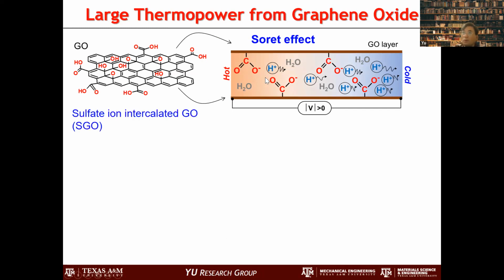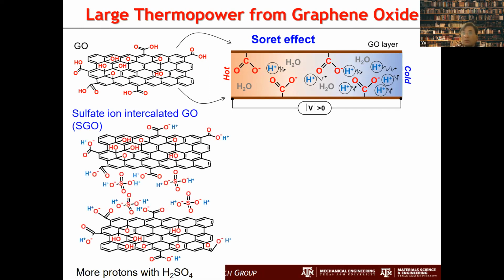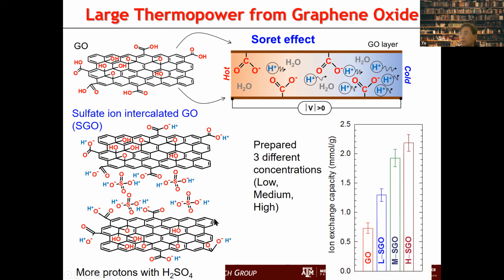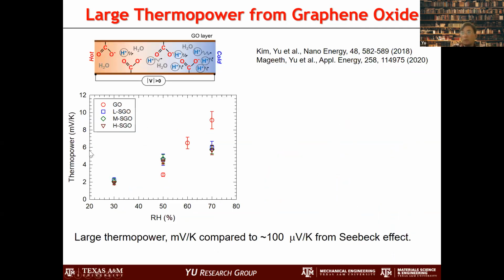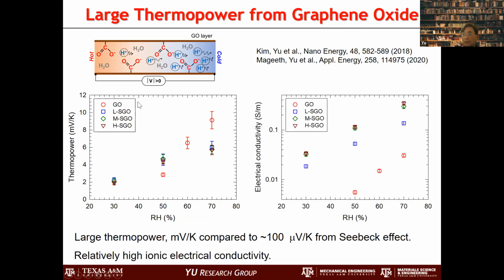So we added more by putting sulfuric acid in between, and then we can raise the concentration of protons. So we have a pretty large number of protons here, and we actually measured it. We increased the proton, and then we tested it using our experimental apparatus, and the thermal power becomes about the same. But in this case, we can create a large temperature difference, so that we can raise the voltage. That's what we are doing.